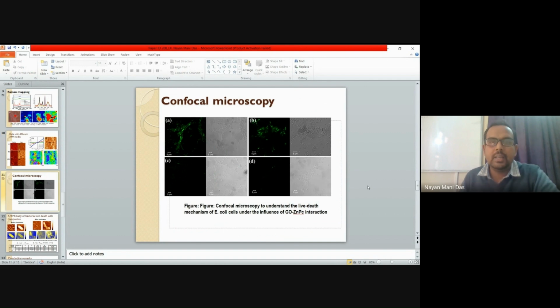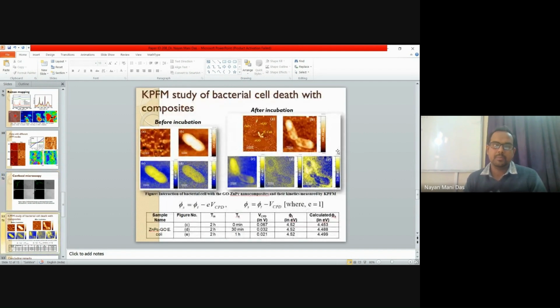Okay, so this is the work when bacterial cells were deposited over our composite films. We could see that when it is in J aggregate form, they were live, but when the bacterial cells were deposited over the composite material which was heated to 585 degrees centigrade, so in the H aggregate form, there were very few live bacterial cells. From there we did the electrical measurements, these KPFM measurements. The KPFM measurements before the incubation, when the composite material was in the J aggregate form, did not show any sort of change even if we do the characterization for a longer time.